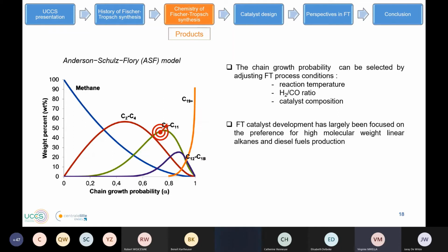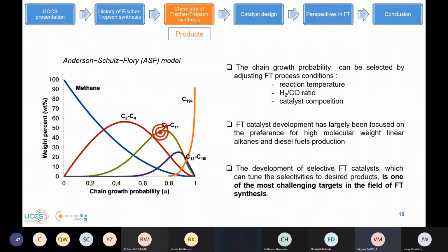hydrocarbons. So depending on the reaction temperature, for example, if we increase the reaction temperature, we are going to limit the chain growth probability. And sometimes also, if we work with a partial pressure of hydrogen a little bit higher, we will also decrease the chain growth probability. So it will also depend on the catalyst development. And so the development of selective Fischer-Tropsch catalysts, which can tune the selectivities to desired products, is one of the most challenging targets in the field of Fischer-Tropsch synthesis.